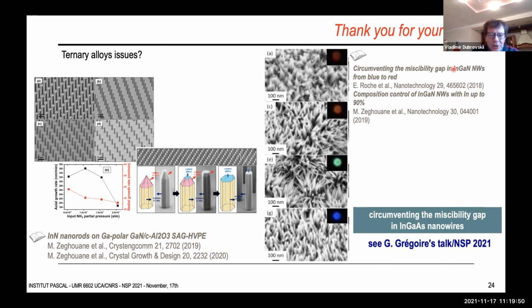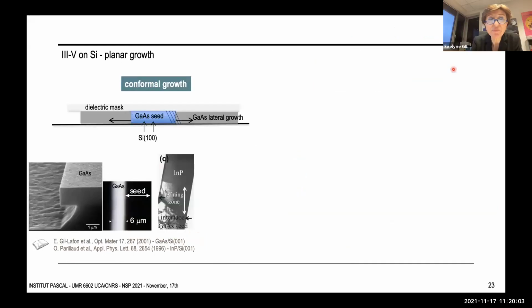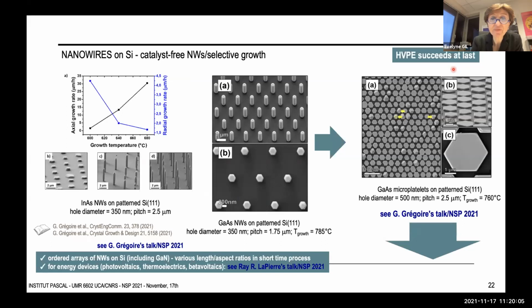But my question is about this selective area grown gallium arsenide nanowires that you showed. So I think they are quite large in diameter. Can you please show them? Yes. Here. So is it critical, or is it just this sample and you can actually reduce the diameter by making the pinhole smaller? Yes, you can use a smaller pinhole, but you also have to control the ratio between the axial extension and lateral radial extension.